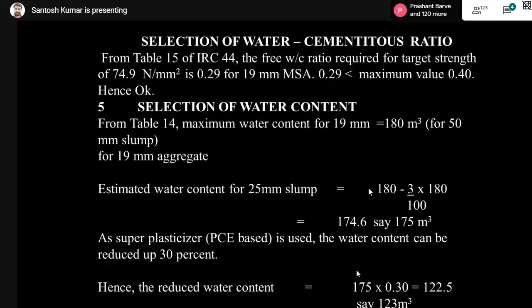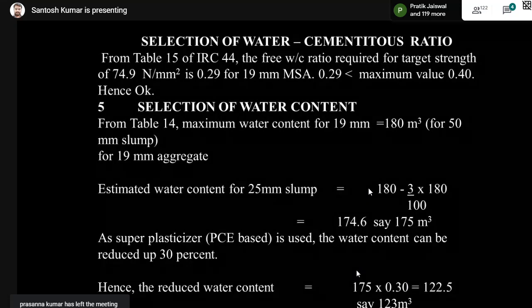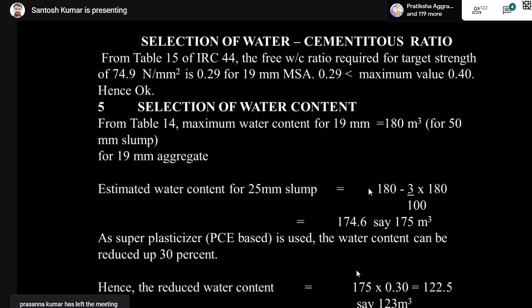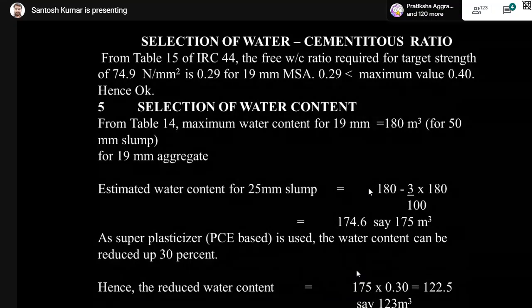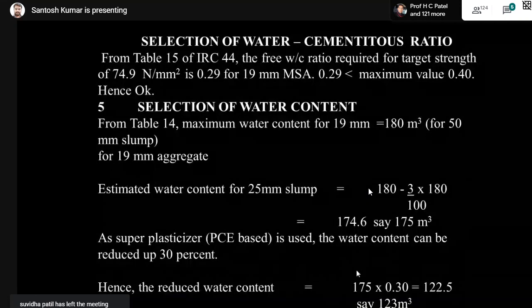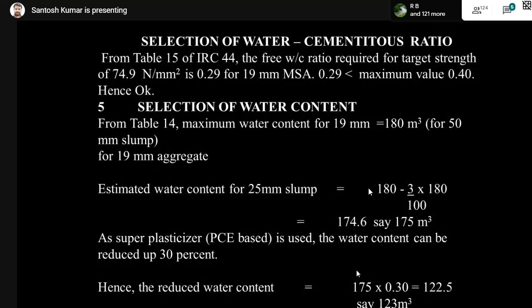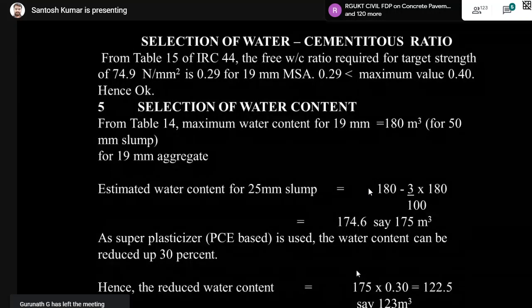So selection of water cementitious ratio. Again, this table 15, as I told you, is given for a water cement ratio of 0.30. We are using in this design 0.29. So in this 0.29, you can see here selection of water content, the maximum water permissible in table 14 is 180 kg per cubic meter for a slump range of 50 mm. But we need 25 mm slump, 15 to 40 mm is required. We don't require 50 mm slump. So for reduction of 25 mm slump, the estimated water content will be 180 minus 3% of water. That becomes 175 kg per cubic meter.